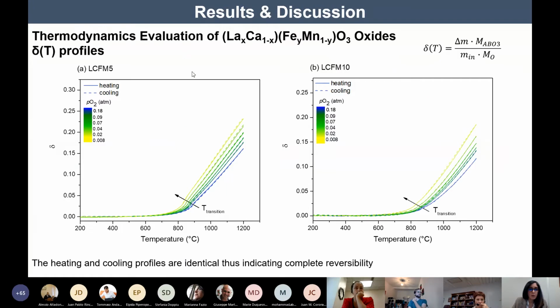We determined all the delta T profiles for all the materials. Here I just briefly reported the ones related to the co-doped samples, just to show you what the delta T profiles look like. We could see that the heating and the cooling profiles are basically identical, indicating the complete reversibility of the reaction, and also the fact that the material was under equilibrium conditions during the overall analysis.